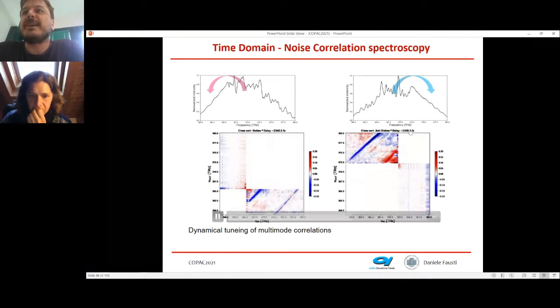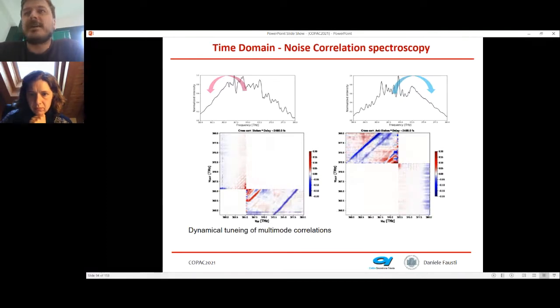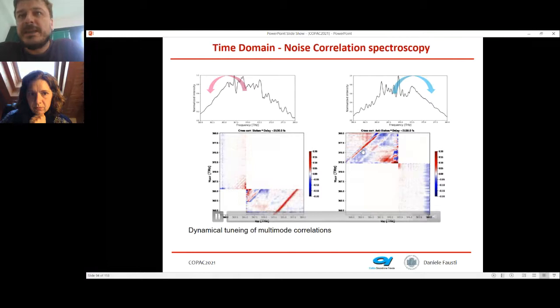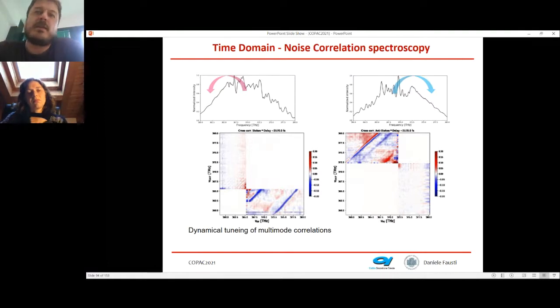And you see that if you do the experiment at the same time, you see that basically the lines associated to the same phonon, they oscillate in anti-phase. So you can see the coherent response of the phonon, and you can see the evolution of the momentum of the motion of the phonons in this respect. How to deconvolve the statistics is a subject that we are working on now with the group of Shaul Mukamel, and I don't have a specific answer yet, but you can measure this fluctuation spectroscopy with the time resolution, and you have a time resolution which is as short as your pulse, but a frequency resolution which is as good as the width of one of your spike in this.